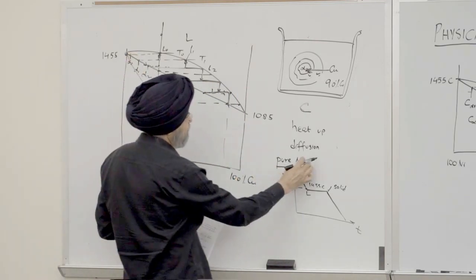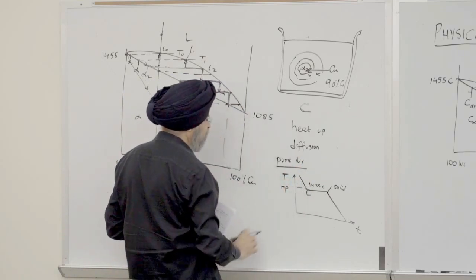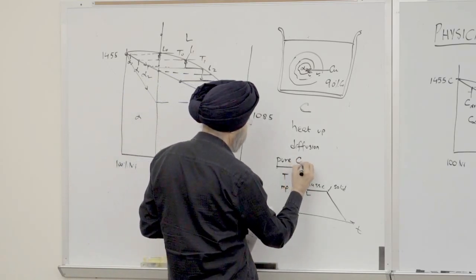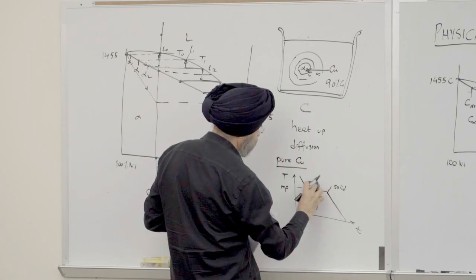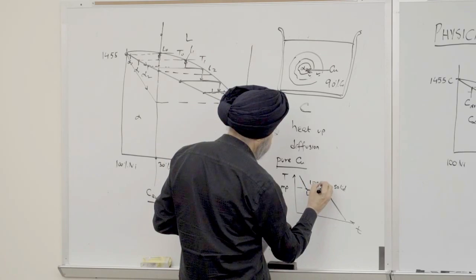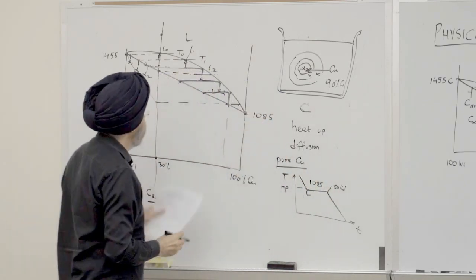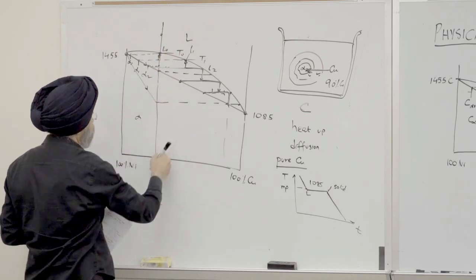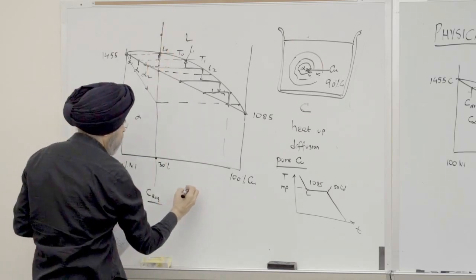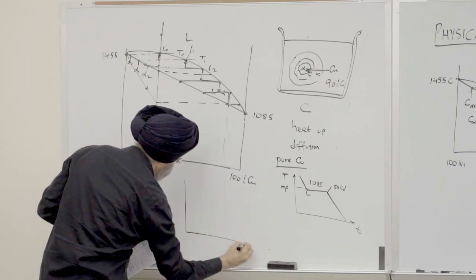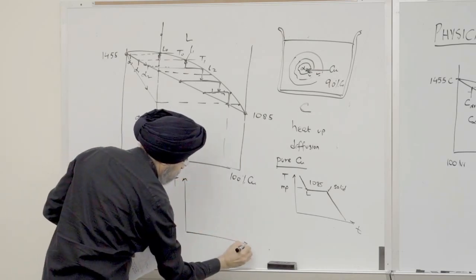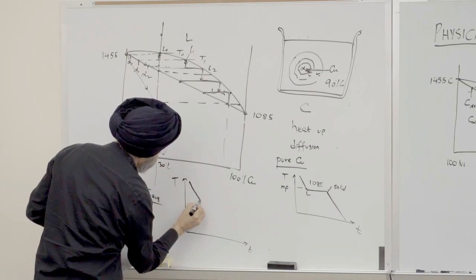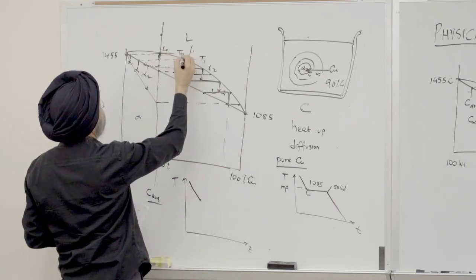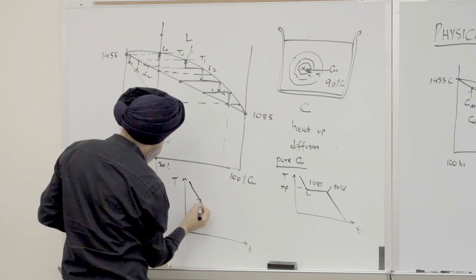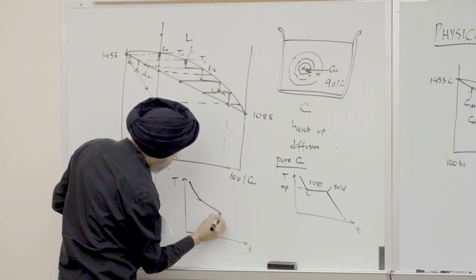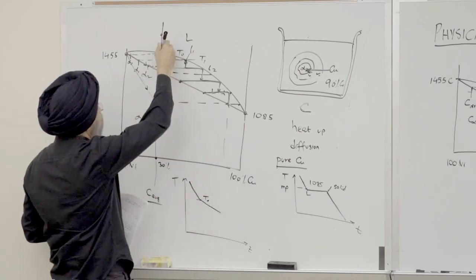Again, we can do the same thing for copper. If you do it for copper, you get a similar curve, and this is 1085. So you get that point. In between, let's say we have this composition, and we're cooling this alloy. What you will get is the temperature versus time plot. You'll be cooling down, and when you get to this temperature T0, the cooling rate will slow. So this is T0. You keep cooling down slowly.